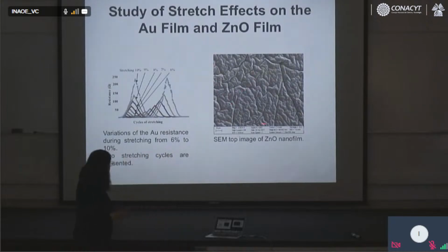Now, this is the zinc oxide when it's stretched. Very interesting. I was thinking my idea is not good and will not work because when I looked at the SEM microscope, there were so many cracks in the zinc oxide. Gold also, this is the resistance of the gold layer based on the stretch. You stretch 10% or less, 6%. The resistance is less and less. So the gold is changing the resistance.